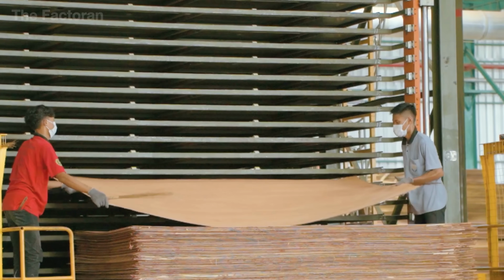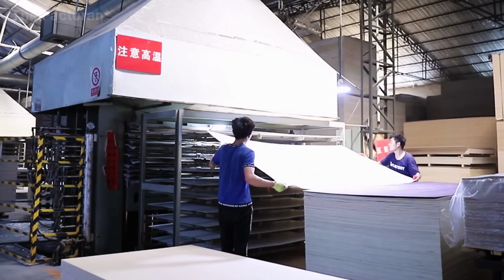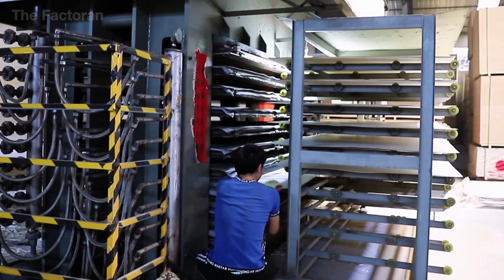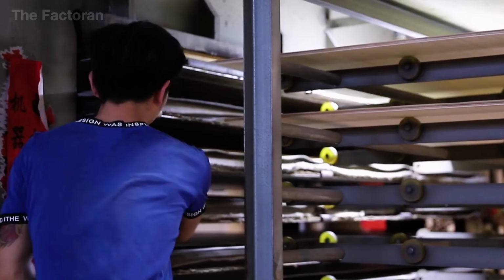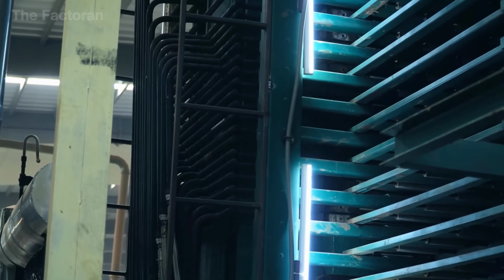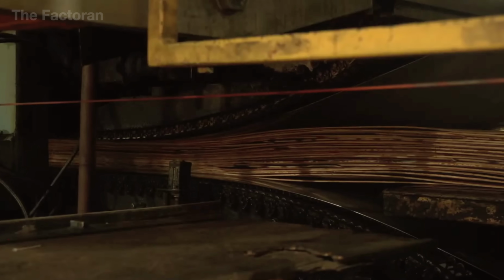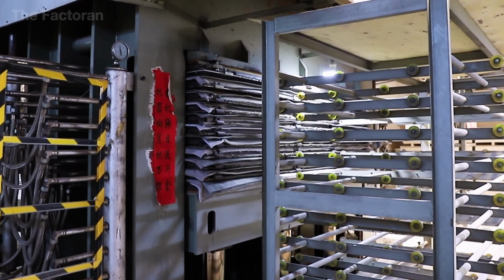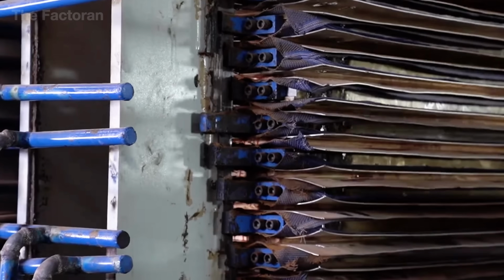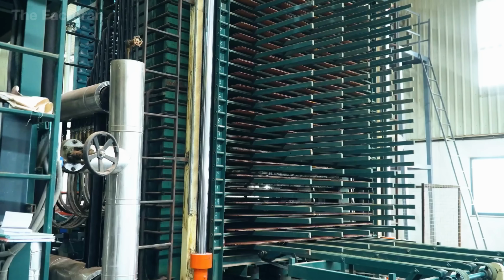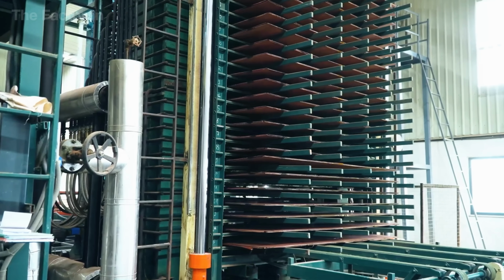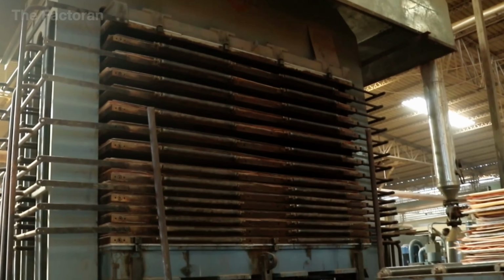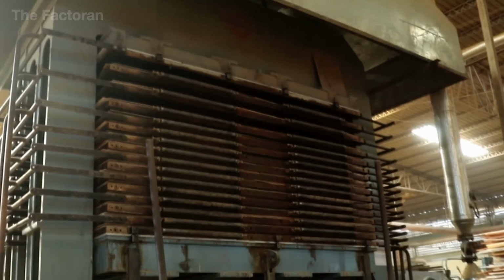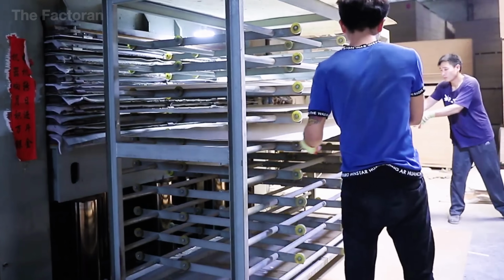Hot pressing time varies with panel thickness, usually lasting 4 to 7 minutes per cycle. Throughout the process, sensors constantly monitor temperature and pressure, adjusting automatically to avoid overpressing, which could cause cracks, or underpressing, which would leave bonds incomplete. When the cycle ends, the plywood sheet emerges flat and smooth, with uniform thickness and high mechanical strength. It is at this stage that plywood truly takes shape as a finished engineered material, combining the strength of many layers of wood, yet performing as one solid whole.